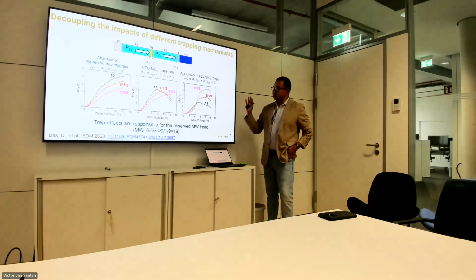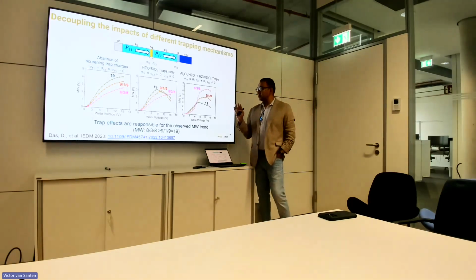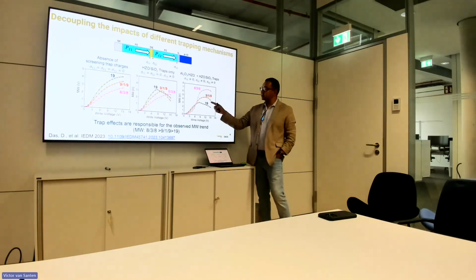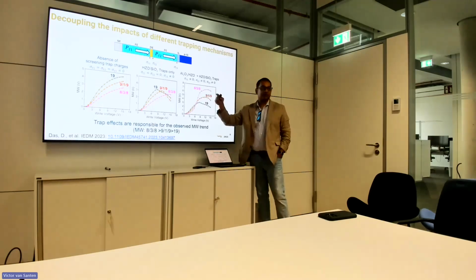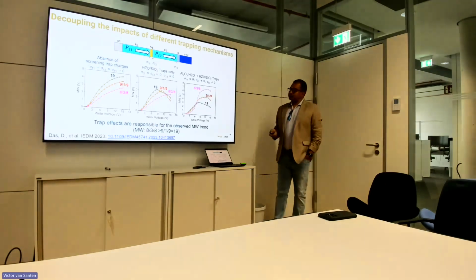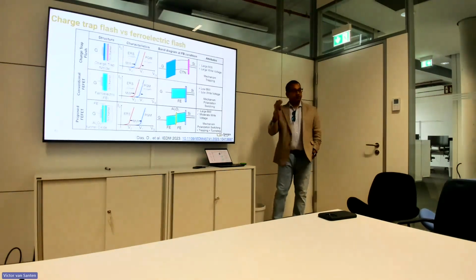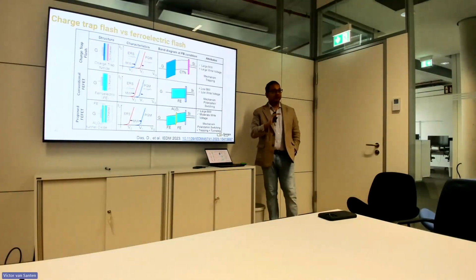But the reason I tend to believe the simulation is that in all cases, all the parameters were the same except for one parameter, the trap density, which was changed. Okay, so this basically shows we think that the additional memory window is coming because of the defects or charge traps that we have at those interfaces.